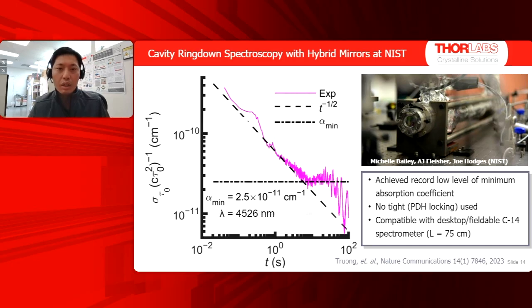And for a linear ringdown, linear spectroscopy or linear interaction with gases in a cavity ringdown setup, that is the lowest absorption coefficient that has been reported. And that was enabled solely by the lower loss mirrors at this wavelength. We can talk more details about the spectrometer, but it fundamentally is a Fabry-Perot cavity. It's 75 centimeters long, and this really opens up the possibility of doing some exciting science that otherwise would have to be done at, say, accelerators. That would be like a facility-sized spectrometer.